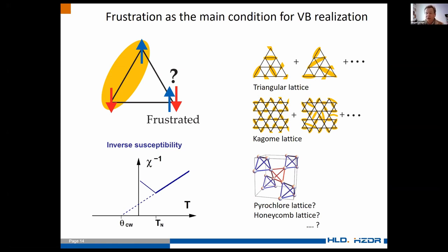So you have to have these dimers, and these dimers, this spin singlet, can fluctuate, and this fluctuation creates this very exotic ground state. This can be in a triangular lattice, a Kagome lattice, as I said, or in Kitaev honeycomb-like materials, or even maybe a pyrochlore lattice, because here we can also think about these dimers. What is important is the ratio between the Weiss temperature and the Néel temperature, which gives you the ratio of frustration.